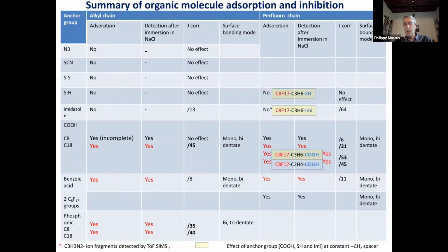So now if we look at the correlation between this systematic study using surface analytical techniques and the corrosion measurements, this is shown here. Now you have to look at what happens in terms of corrosion current when, yes, there is adsorption, and yes, adsorption remains after exposure to the chloride solution. And this is the number by which the corrosion current is divided. And you can see that there is a very big effect when you have these two yes in red. Here it's divided by 45, 35, 40, 21, 53, 45. So there is a very strong effect and a very good, direct correlation between the key features, which are adsorption, nature of the chemical bond, and effects on corrosion.